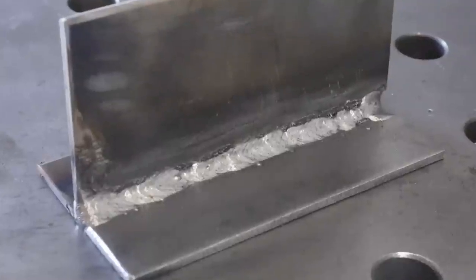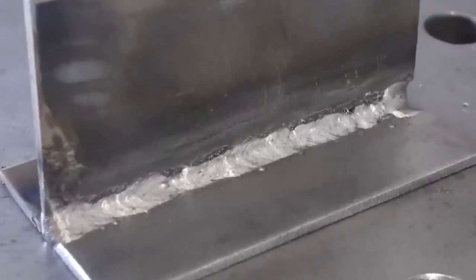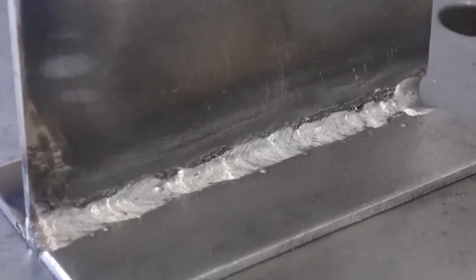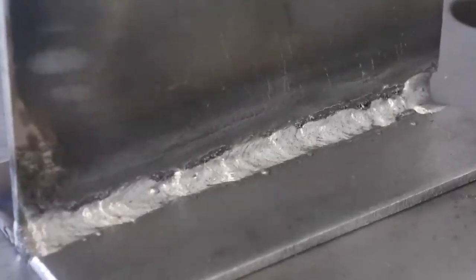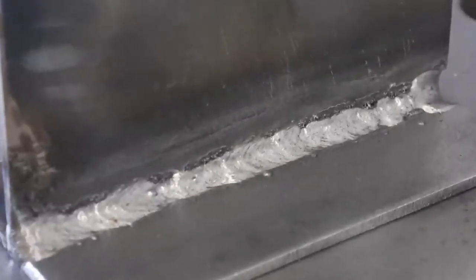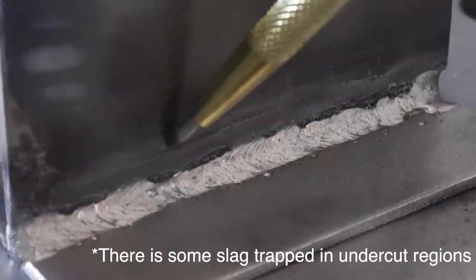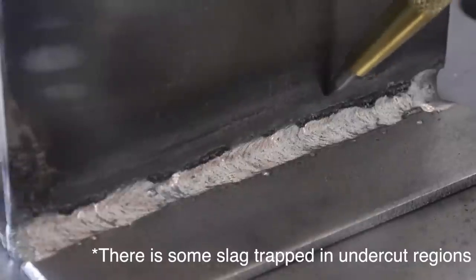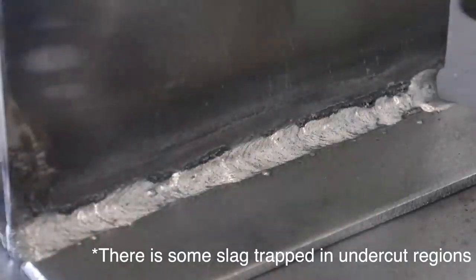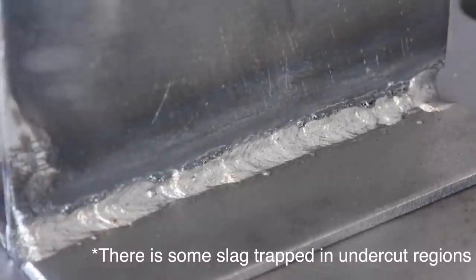Here's the result of that weld. It came out much better than the first. It's fused to both sides of the plate all the way along. Honestly, it's probably good enough for a lot of things. But I do have a little bit of undercut. Now, undercut is where you've melted more material out than you were able to fill back in. And the biggest reason that I think this happened in this case is that it was turned up so high on this thickness of plate, I had to move really quickly.